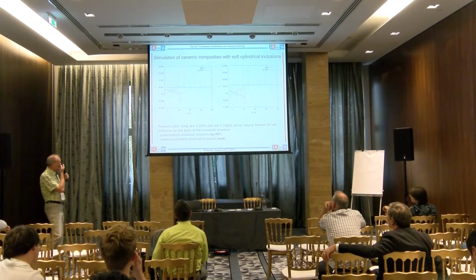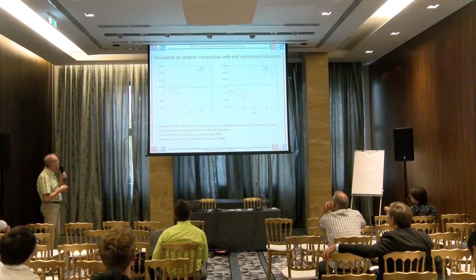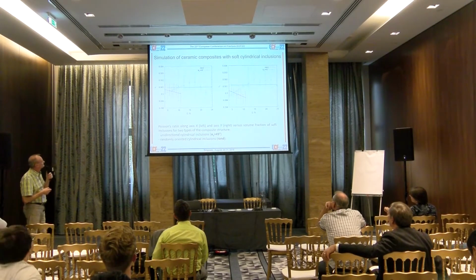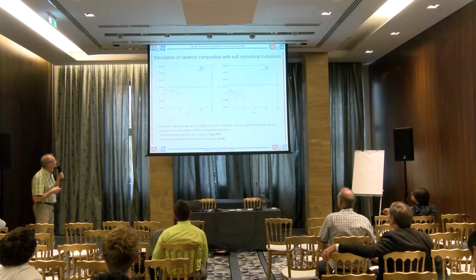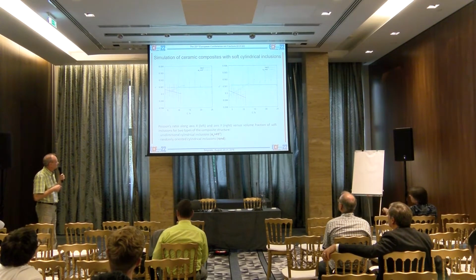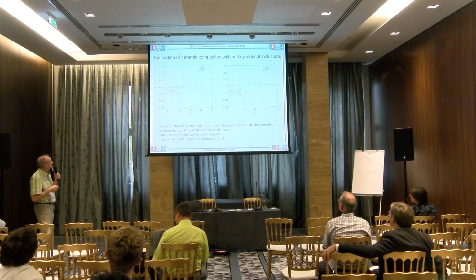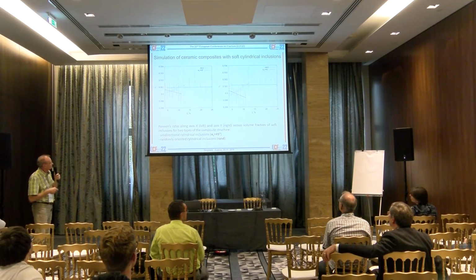And the most interesting result is for the Poisson ratio of such a specimen. You can see that for random position, we have a smaller volume fraction, and it looks like it is descending. And for the unidirectional structure, it is approximately the same, but with a very large scatter.